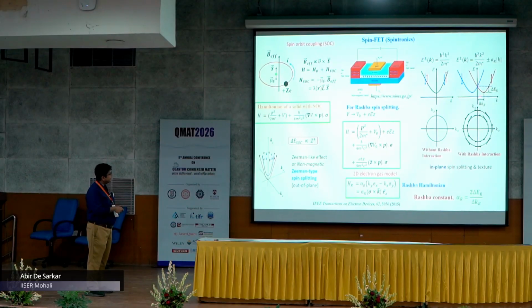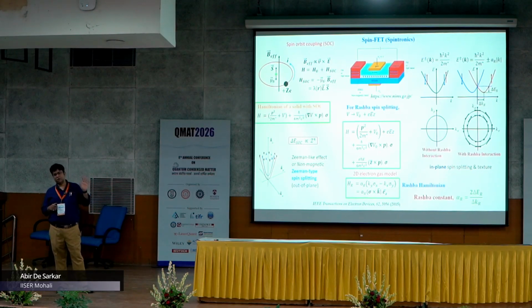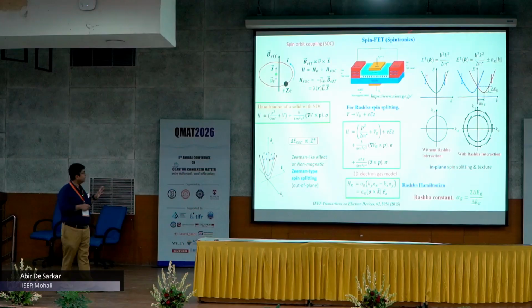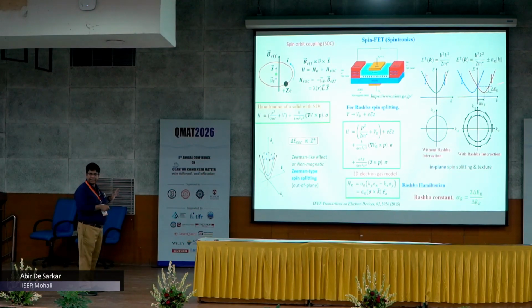This is the energy splitting and the momentum offset, and this momentum dependent spin splitting is quantified by the Rashba constant. So, the higher the spin-orbit coupling, the higher is the Rashba constant. And now this channel material needs to be a Rashba semiconductor in order to be able to control the flow of spin from the source to the drain.